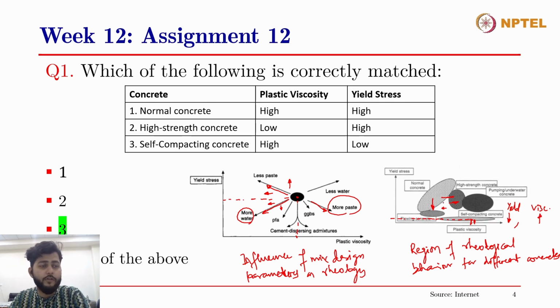Again, you need to also understand that self-compacting concrete mixes also contain a lot of cement. The cement content in these mixes is very high as compared to normal mixes. Therefore, the viscosity increases ultimately. But then you want a higher slump flow in this case, so you have to decrease the yield stress as well. In order to decrease the yield stress, they use a lot of superplasticizer as well. So this is how you can distinguish between the rheological behavior of different types of concrete.